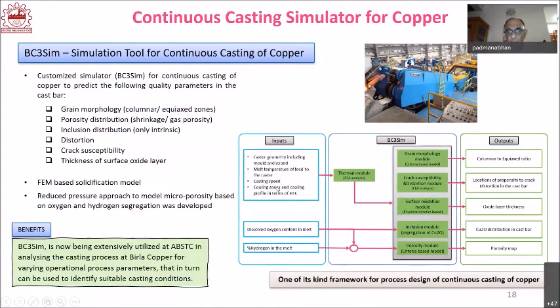For example, there will be some water cooling of the slab that is coming out, and as the casting is coming out, there will be vertical guides which are made of copper. This is the copper block, and the top and bottom, as the slab is coming out, is made of steel. So it is a complex heat transfer problem, and copper extracts heat more quickly than steel. Anisotropic behavior is possible. But the problem is simpler in copper than steel because the size of the billet or ingot is much smaller. And therefore, what I talked about as the columnar to equiax transition becomes less of a challenge here than in the case of the steel industry.